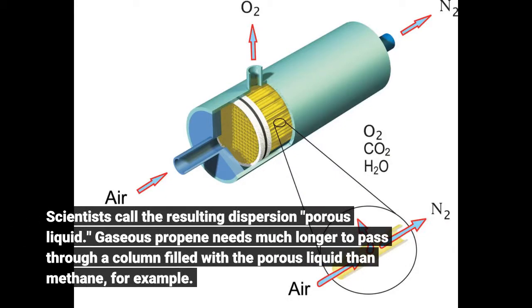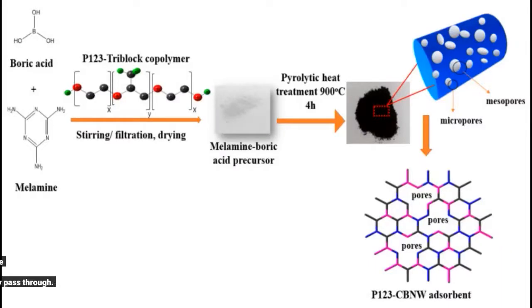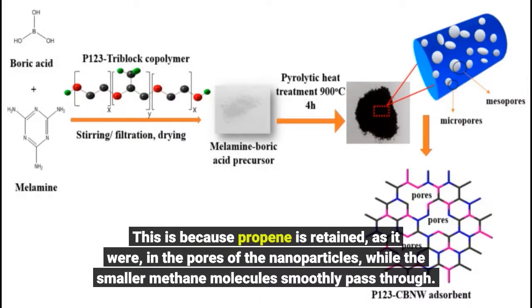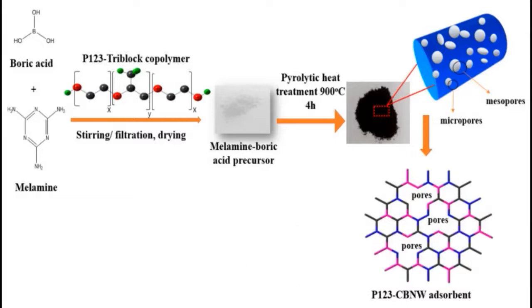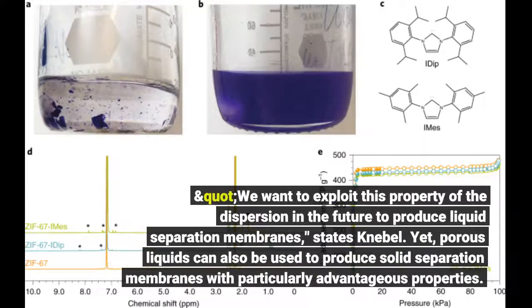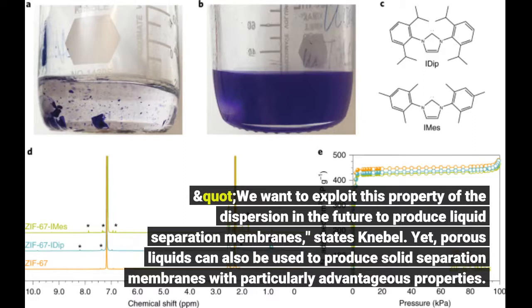Gaseous propene needs much longer to pass through a column filled with the porous liquid than methane, for example. This is because propene is retained, as it were, in the pores of the nanoparticles, while the smaller methane molecules smoothly pass through. We want to exploit this property of the dispersion in the future to produce liquid separation membranes, states Knebel. Yet, porous liquids can also be used to produce solid separation membranes with particularly advantageous properties.